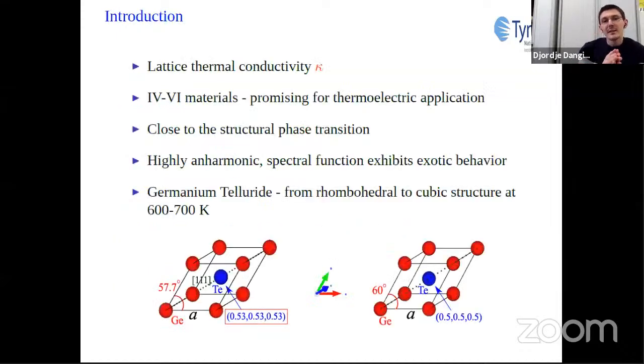There are many reasons why one should be interested in modeling lattice thermal conductivity. For our group in particular, we are interested in improving the thermoelectric efficiency of the materials, and one of the most promising ways of achieving that is to reduce lattice thermal conductivity. IV-VI materials are one of the most promising thermoelectric materials, mostly because of their low lattice thermal conductivity, which is a consequence of them being close to the structural phase transition.